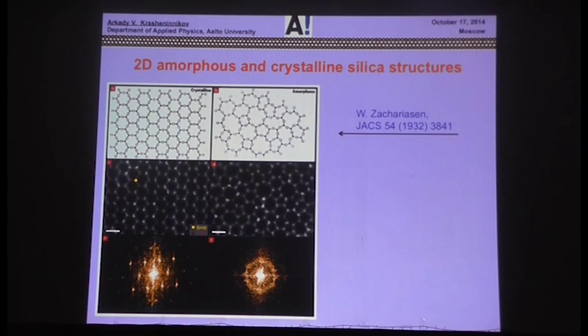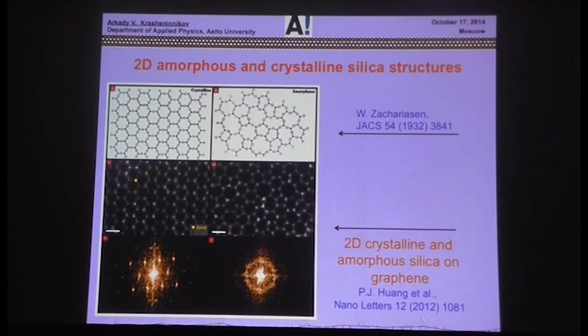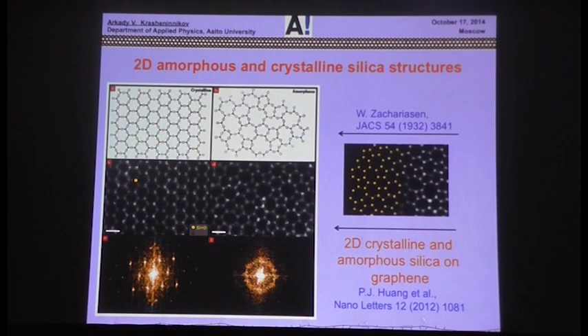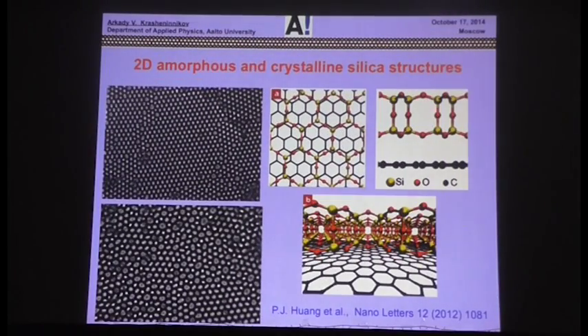Interestingly enough, our co-workers looked a couple of years ago at graphene grown on copper, and surprisingly they saw a lattice with a unit cell size much larger than graphene was supposed to have in TEM. And actually later on, from EDS analysis, we realized that it's not graphene, it's actually silica, SiO2 on graphene. And this is the top view, and this is the side view of the structure and perspective view. So essentially, you have a silica bilayer. These are oxygen atoms, these are silicon atoms, this is graphene, and this structure can be crystalline, with small crystallites here separated by a grain boundary, or amorphous.